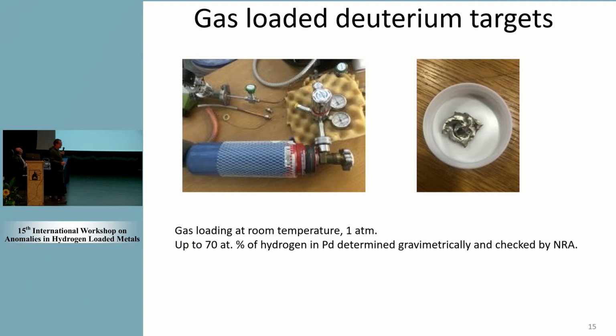Another way to get hydrogen or deuterium into the target is with palladium. We can just put it in the gas, and if you have a good palladium, this is what comes out. You put it in completely flat, and then it absorbs 70 atomic percent of hydrogen, and it's all deformed, squashed, and difficult then to measure, but that's what you get. So at room temperature and 1 atmosphere, you get 70% of hydrogen per palladium atom. And then we can weigh this, and weighing it determines very well how much hydrogen is in.